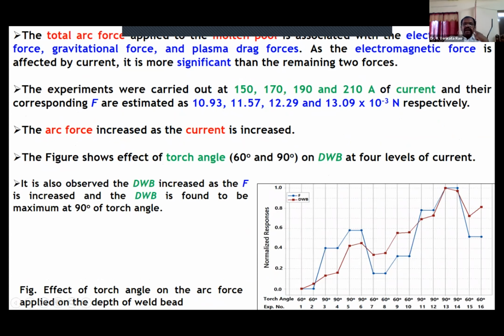See this one. Experiments 1 and 2 were conducted at 60 degrees, 3 and 4 at 90 degrees. Like that, the position at which each experiment was conducted, the arc angle and the experiment number are also given here. When the arc force is more, the depth of the weld bead is also more. That is what we are seeing from 1 to 15. At 15 and 16 you also have 60 degrees, but the current is more. The arc force is directly affected by the current. So the effect of current on the arc force is more.